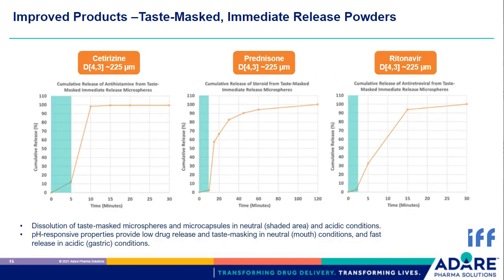And looking at the dissolution profile, it is evident that Optimum technology is able to address the most challenging formulation target, balancing taste masking and immediate release profile. As you can see, taste masking is ensured by minimizing the release in the first minutes after the administration, when the dosage form is in the mouth. Drug is then quickly released in the stomach in order to ensure bioequivalence with the reference product, usually represented by an immediate release dosage form. Obviously, also sustained or delayed release profiles can be developed by selecting the appropriate functional excipients.